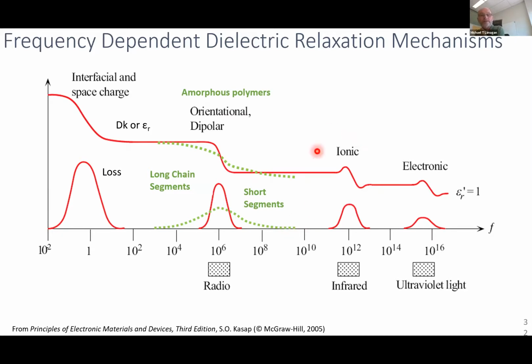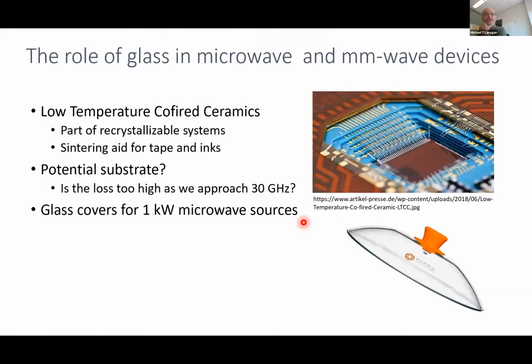Next, I would like to talk about the ionic contributions to the dielectric response, either the permittivity, the real part, or dielectric constant, or the loss, and how these tails will come into the 5G range. Let me just talk about glass. It's a really important material in microwave and millimeter devices. It's used a lot in something called low temperature co-fired ceramics. These are used in very sophisticated packages as we get to miniaturization for 5G. All cell phones have low temperature co-fired ceramics as part of their package, and those packages have a glass component as well.